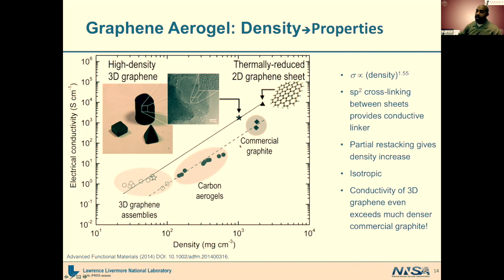What we found, though, is that with many of the carbon aerogels and even graphite carbon, the orientation or the way in which the defects within the carbon are arranged plays quite a role in what that baseline conductivity is. And so that's what really accounts for this difference between your more disordered carbons here and your highly ordered carbons, which would be more of your graphenes up here, and you do get this offset in terms of the conductivity.